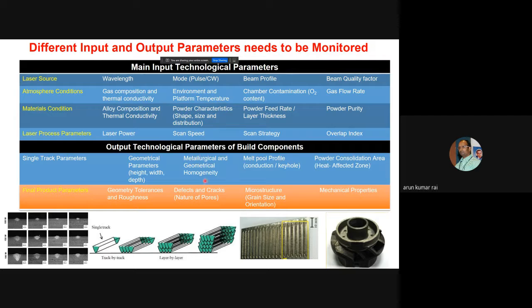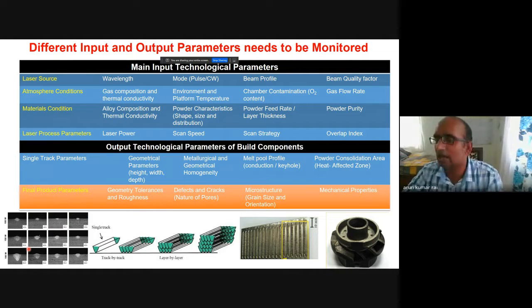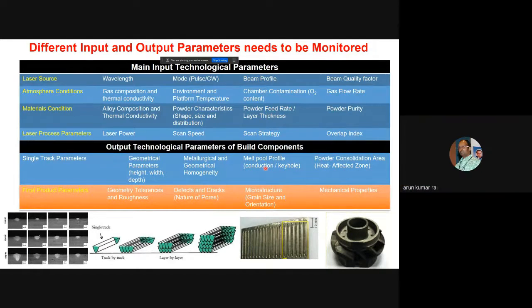And next we look at the metallurgical and geometrical homogeneity. Metallurgical means whether there are any microstructural issues or defect formation. Then whether the geometry is getting distorted or proper geometry is formed. Then the melt pool profile, like I have told, conduction mode and keyhole mode. Keyhole mode is not preferred because it leads to porosity formation, and conduction mode with poor wettability is also not preferred because it will lead to detachment. So all these things have to be looked at before final printing. Then next is the powder consolidation area, basically the heat affected zone. When you are printing, some of the powder will not melt but will be sintered. That sintered powder area can lead to defect formation.